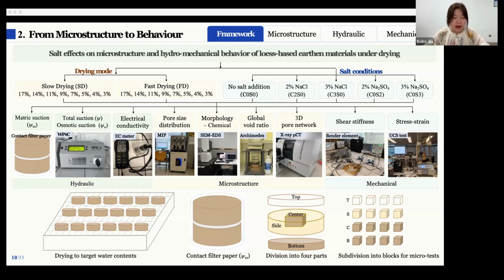elemental analysis. And we also considered that some very small pores cannot be accessed by mercury intrusion, so the void ratio obtained from the MIP is theoretically smaller than the actual value. So therefore, we used a volume displacement method based on the Archimedes principle to obtain the global void ratio to calibrate the MIP data. And in addition, the non-destructive X-ray CT imaging provides the three-dimensional pore structure information with a resolution of 10 micrometers. In this study, it can also extend the pore size distribution beyond the range of MIP.